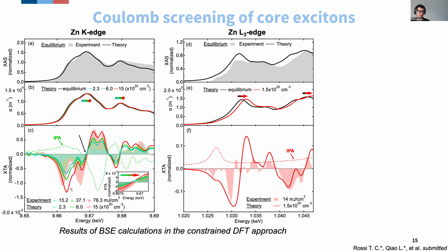And the bottom panel is the simulation of the pump probe, again with theory in continuous curve and experiment with shaded curves. You can see that we can get a great agreement between experiment and theory, both at the zinc K edge and at the zinc L3 edge. And if instead of using this code that includes excitonic interactions, you use the independent particle approximation that does not include excitonic interactions, what you get are the dashed curves. So you can see that it's completely missing what's happening experimentally. So the inclusion of core excitons is crucial to be able to interpret what's going on here.